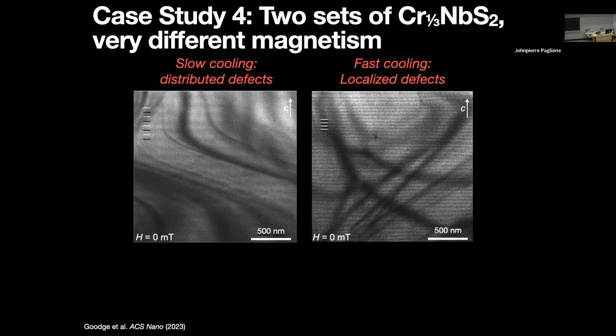You can heat it up back to the growth temperature and quench it, and you get a perfect root 3 by root 3 signal from Raman. You can then take that and, as you're saying, start to back off on it and cool it, and it starts to convert back.